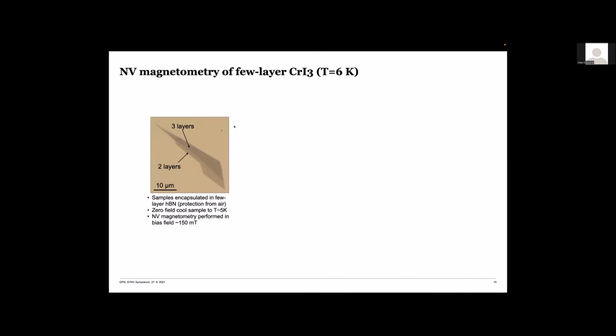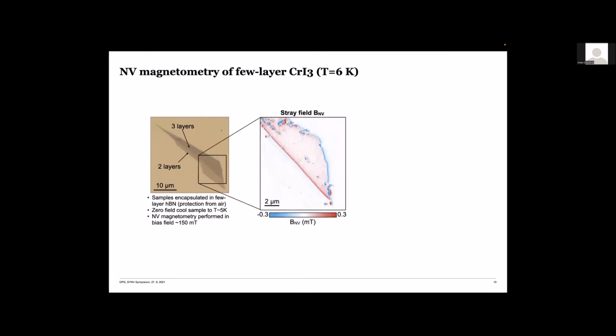So what we worked with were these exfoliated samples that we got from the Gibertini group at the University of Geneva. Here's one example of a flake that was exfoliated into 2 regions here, one being a tri-layer and the second one being a bilayer flake. And here you see the results we get when we scan our NV center over these flakes with the technique I don't need to repeat. So essentially what you see here in color code is the stray magnetic field projected onto the NV axis.